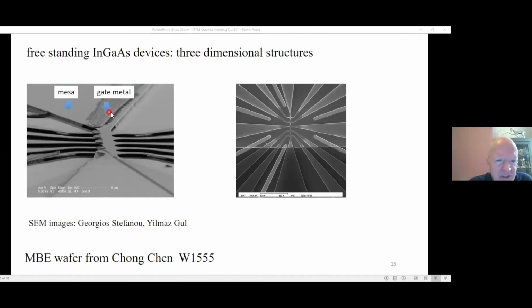A few more SEM images. This is a kind of a failed device. The gate metal has just missed the top of the mesa. These haven't collapsed. The latest devices, this is another SEM image. This is looking down on the device. These are completely freestanding. These are metal contacts that would be used for perhaps E-beam defined devices. This is all optical lithography. This is a kind of a large area gate over here. But you can see where the etch has gone through underneath here. This is completely freestanding. Very, very nice structures under the microscope. Slightly difficult to measure.